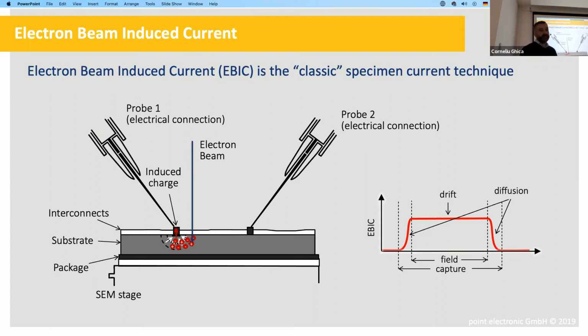And if the material has a band gap, and this is one of the main requirements for the technique to work, the material must have a band gap, then you would excite electrons from the valence band to the conduction band. So we will induce electron hole pairs. And that's why it's called an induced technique. So we don't rely on current from the primary beam, we rely on new current induced by the energy loss of the primary beam. And that happens always in a microscope when we have a semiconductor, because it has a band gap.